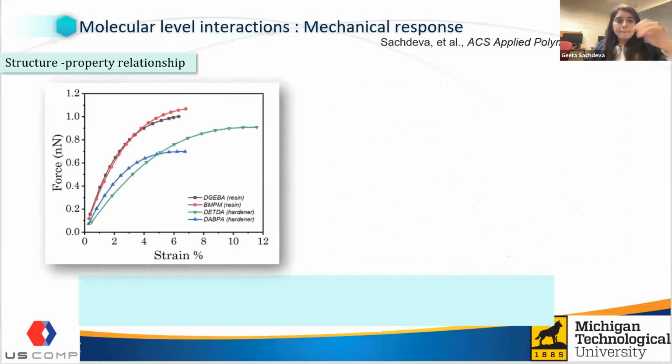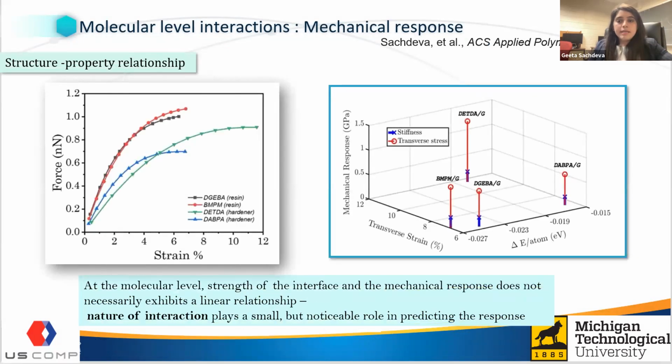In mechanical response, the data obtained from the pull-apart test suggested that there is some relationship between structure and the monomers. We found that the hardener DETDA especially has the lowest population, but it has the highest breaking point because of its planar structure. It will have more pi stacking at the surface because of its planar structure. That's why it has a higher breaking point.